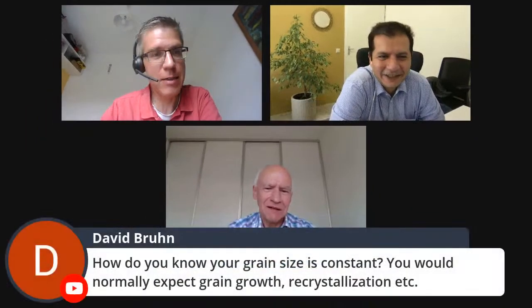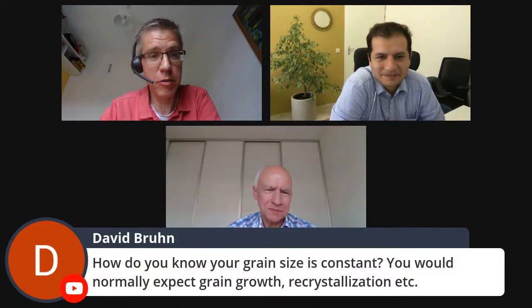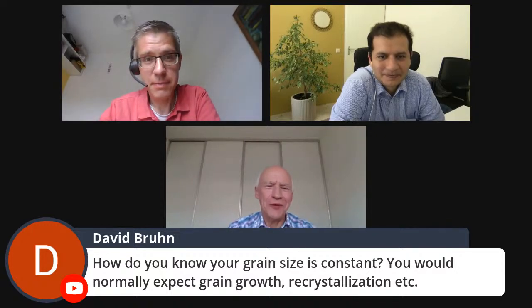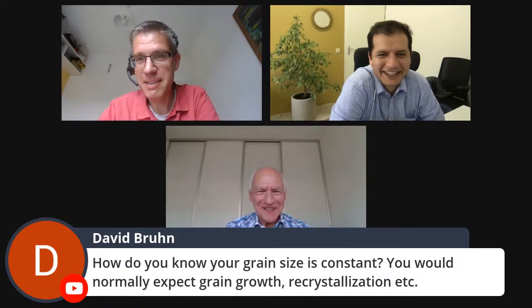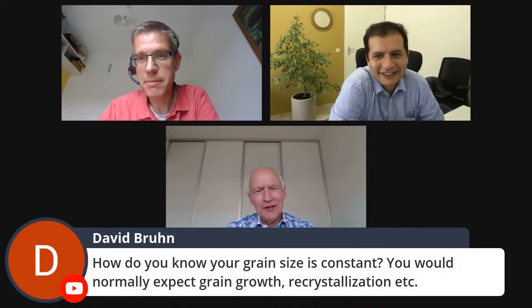David Brun asked a question. He mentioned the grain sizes, and he asked, how do you know your grain size is constant? You would normally expect grain growth, recrystallization, etc. A fantastic question, David, from a man of experience. You're absolutely right. During plastic deformation of rock salt, under conditions where fluid-assisted recrystallization can operate, it starts and gradually consumes the microstructure and will lead to a new grain size, which ends up more or less in the transition between dislocation creep and pressure solution. And it gives rise to a relationship between the recrystallized grain size and stress. That's what you see in experiments.